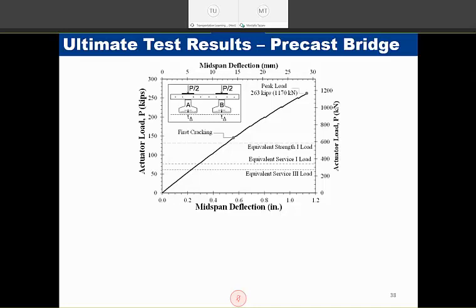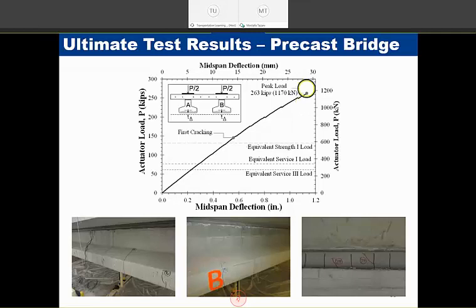In this slide, I'm showing the force deflection behavior under the ultimate testing. The first cracking of the bridge was observed at a load higher than the actual strength limit state. We stopped the test at 2 times the actual strength limit, and minimal damage was observed at 2x the strength limit state. Our conclusion was that this option is viable, and it could meet all of the actual requirements with a good safety margin. So the overall conclusion regarding the precast bridge was that it was viable and can be used for VLD.